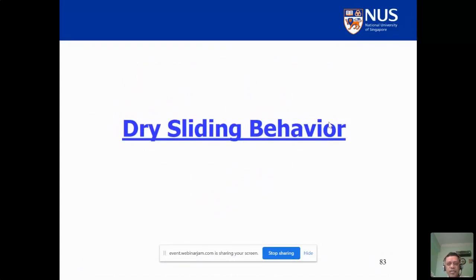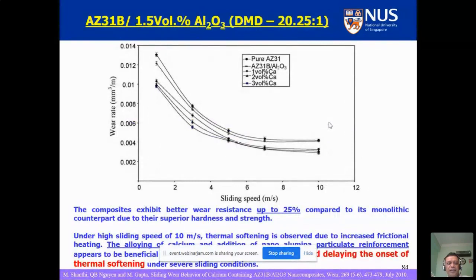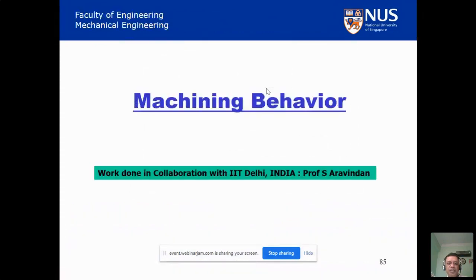Now, another property of importance for the composite is the dry sliding behavior. And we again work in collaboration with some of our colleagues who are experts in tribology. And we see that just by putting about 1.5% of Al2O3, you are able to improve the wear resistance by 25%. And if you add another 3% calcium, you increase the performance by another 25%. So now your life becomes 1.5 times of the original life. So again, the nano reinforcement helps by modifying the wear mechanism of the base material.